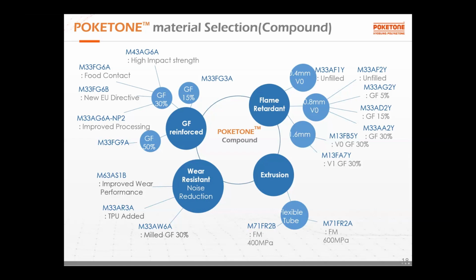Also, recently we've got a lot of requests for the flame retardant grade for application like electric vehicle. So we have a portfolio of flame retardant grade across various thickness. And we also have a wear resistance grade. And naturally polyketone has a good wear resistance. So by adding silicone or TPU or mineral, we can improve further our wear resistance. Also, we have a flexible tube application with a very flexible flexural modulus around 400 to 600 megapascals.